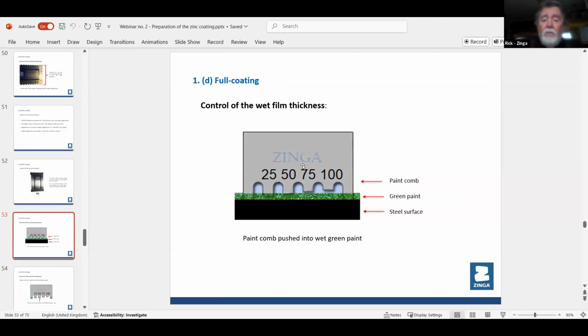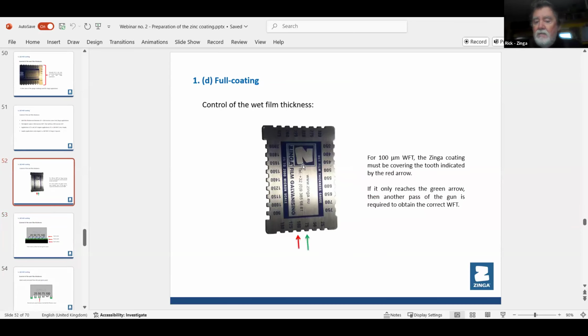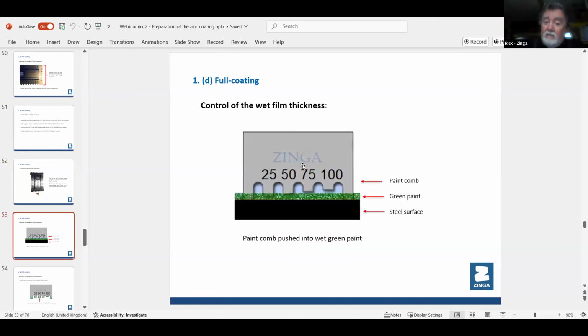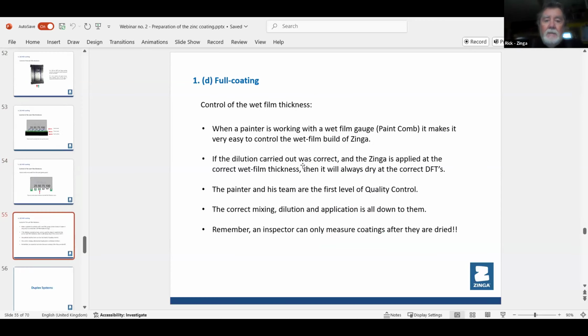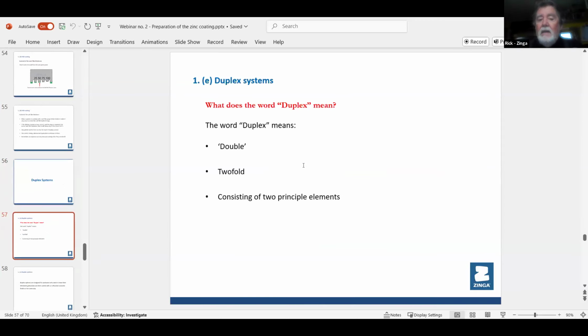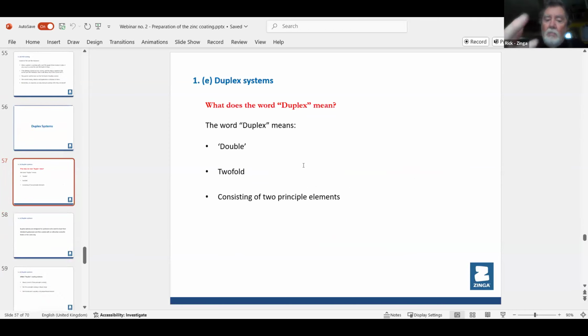But what I'll just quickly say here, when you're checking with this, it varies from company to company. Some guys will do a pass and their painter has got a very fast hand, so he might do one pass and check it again and it's still too low. Whereas in another company, the painter does one slow pass and he measures, and that's perfect. So where you measure 75, some guys might take 2 passes to get to 100, and others take 1 pass. That's why you test and check it. It's control. And then duplex again. Duplex just means 2 or double.